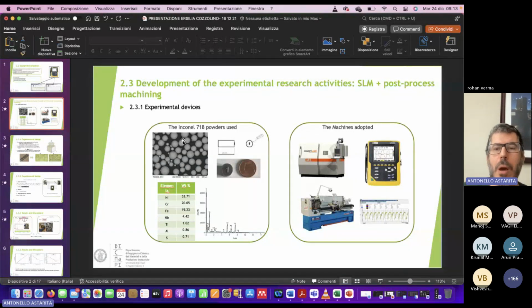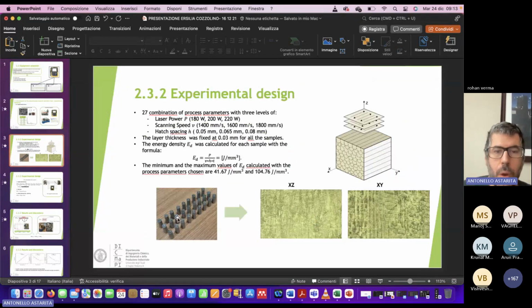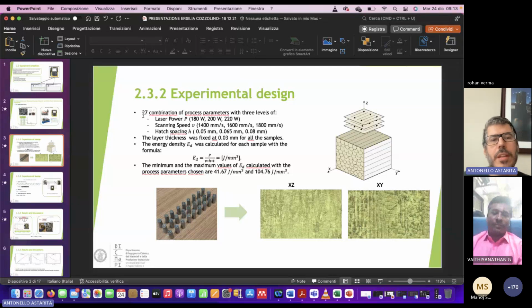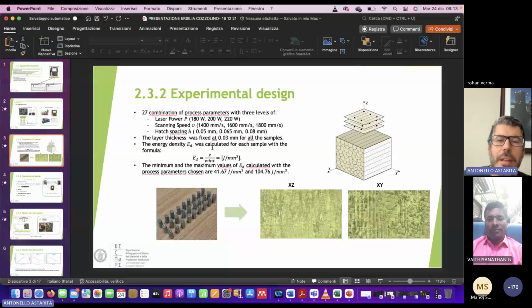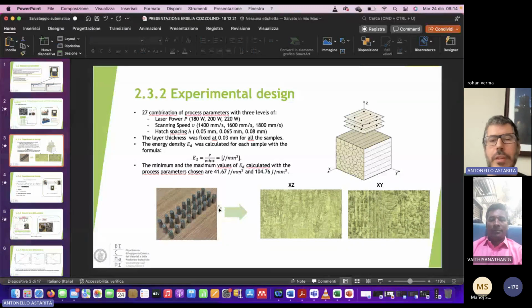So we started from those powders and manufactured some samples, cylinders. Why cylinders? To have a very simple geometry as a reference to measure the specific energy consumption. We printed a lot of samples by varying the laser power, the scanning speed, and the hatch spacing. We did 27 different combinations of processing parameters, and we calculated the theoretical energy density for each condition. This is a very common formula used in 3D printing.